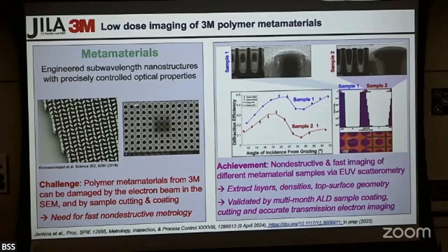This light is less destructive just because you put in less energy to the material? Photon energy is only 30 eV compared to the multiple keVs in an SEM. So 30 eV makes a photoelectron of about 25 eV, and that does pretty much no damage.